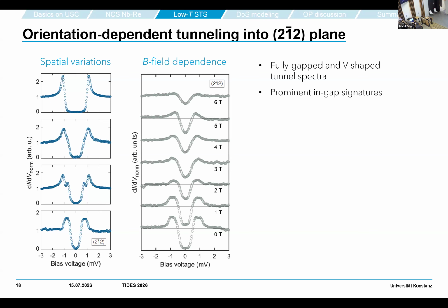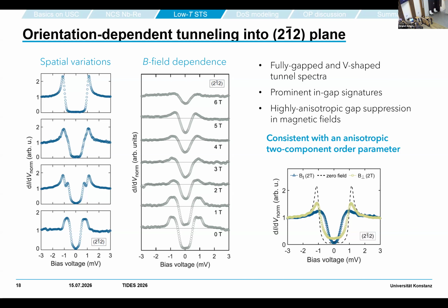Another test that we can do on the single crystals is comparing how the gap fills when we apply the magnetic field perpendicular or parallel to the plane. And here we see a sharp difference. So the dashed curve would be the one that we measure at zero field, close to this fully gapped one, the boring one if you wish. And then when we apply a magnetic field parallel, this is in blue, or perpendicular to the plane, the gap filling is different. These are all hints for an anisotropic order parameter, consistent with a two-component order parameter, an S-wave-like, and also something that is not S-wave-like.